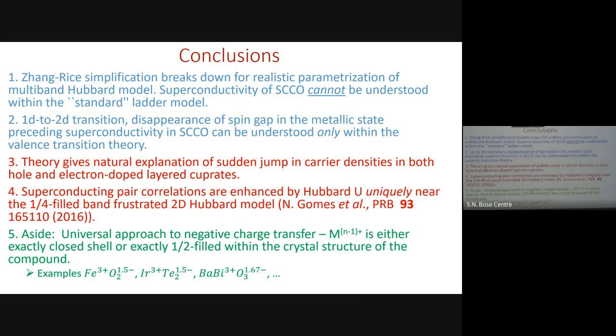So we are claiming that this transition can be explained only with the valence transition theory. Theory gives a natural explanation of the sudden jump in carrier densities in both electron and hole doped layered cuprates. This I haven't shown you, but we said we measure the superconducting correlations at U equals 0, measure it at finite U, it has to increase. So we have a paper, different band fillings, triangular lattice. This increases only at one band filling.